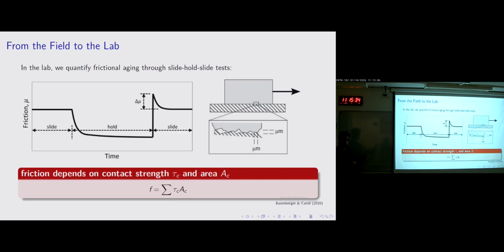When we stop pulling on the block, friction is going to relax. We're going to go into a hold, kind of like in the interseismic period between earthquakes. During that time, it relaxes for a predetermined time that we choose, and then we resume sliding and pulling on the block. That's when we see a sharp increase in the friction coefficient, reaching a peak, before resuming some steady state friction later on. This difference between the peak and the steady state friction, that's delta mu, is what we call and quantify as frictional aging.